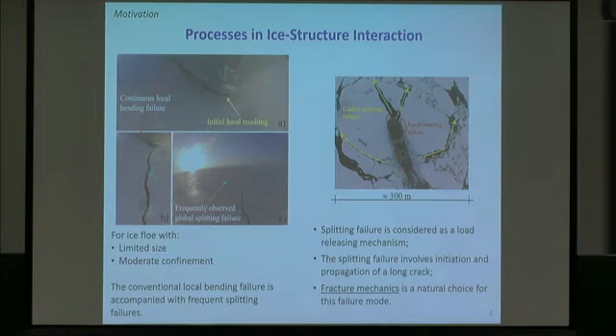And you see crack running forward as you see here. So if I take an example here from Oden in ice, you see a floe. This is 108 meter long, this icebreaker, so the floe is 200 plus. And what can you see when you are breaking forward here? You see a crack developing here, you see another one here. But what you should also recognize here is that there is a lack of confinement on this floe.